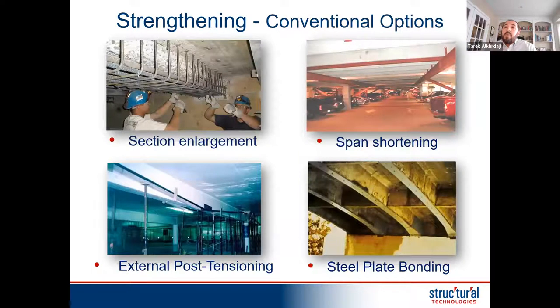These things can easily be done with carbon fiber, and I'm going to show you some examples for these applications. And I mentioned there are many different techniques that we can use for strengthening of structures. One of the most common ones, the top left, is section enlargement. That's basically doweling in steel reinforcement in both directions, chipping the surface to roughen it, then forming and pumping concrete and filling the void. Basically you're beefing up the section by adding more concrete, more steel. By doing that, we add more strength, more bending capacity, more shear capacity, more stiffness. This is very common, one of the oldest techniques we've been using for probably 80, 90 years.